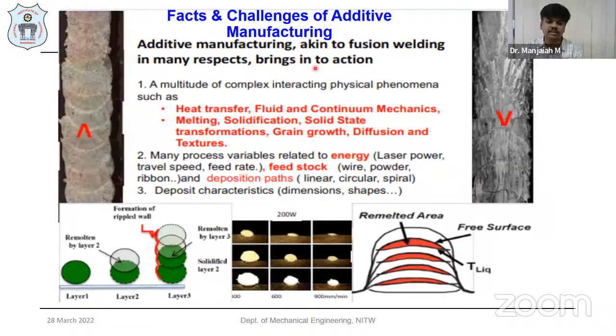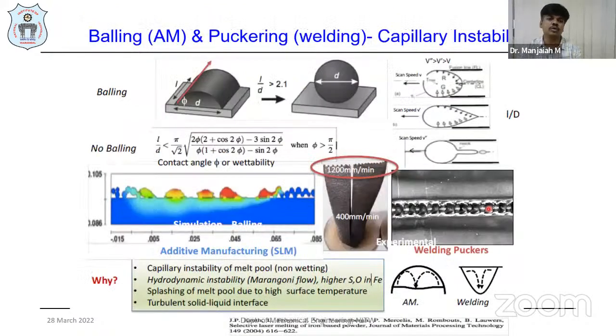Because of these things, there are a lot of difficulties and challenges in additive manufacturing systems, as well as in the deposition characteristics and dimensions and shape changes. You can see these kinds of solidification tracks and the inverted solidification tracks. One is convex and one concave, and they occur because of variations in the energy density. Whether it is higher energy density or lower energy density, these kinds of irregular solidification tracks are going to occur. And balling effect, because of the length to diameter ratio of the beads, a puckering effect may occur in the case of welding and all.